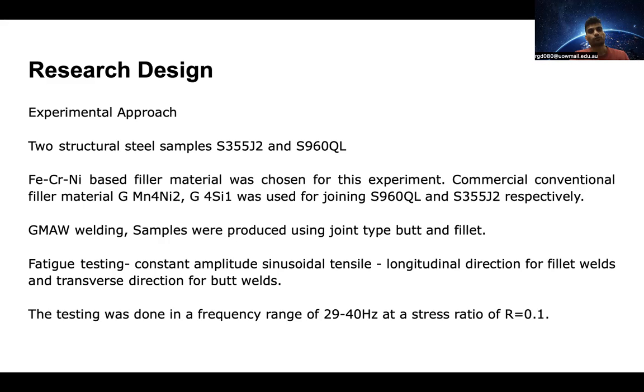After the weld, there was no post-weld heat treatment, I'm sorry. After the weld, fatigue testing was carried out using a constant amplitude sinusoidal tensile wave in the longitudinal direction for fillet welds and in the transverse direction for butt welds. The testing was done in a frequency range of 29 to 40 Hz at a stress ratio of 0.1.